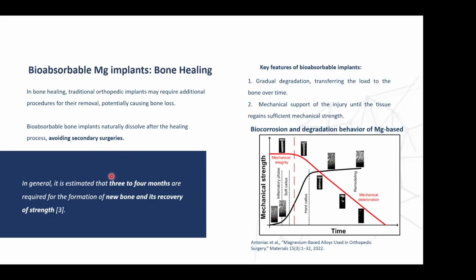So we need to reduce the corrosion rate in this material so that we can allow mechanical integrity before or at least after hard callus of the bone is developed in the actual fracture site, right? So if we can get mechanical integrity still after hard callus formation, then the bone can continue healing as the rate of absorption of the implant is continuing, or it's faster. So actually, the work in bioabsorbable magnesium alloys has been in controlling or reducing the corrosion rate.